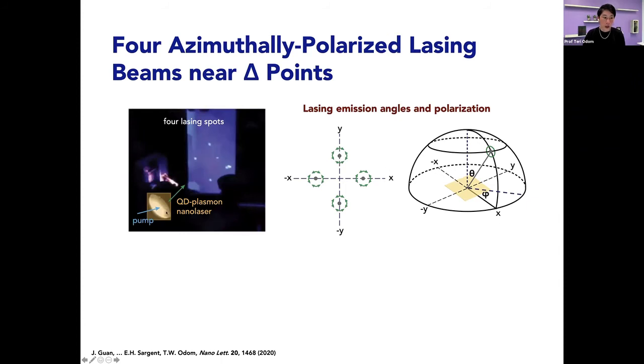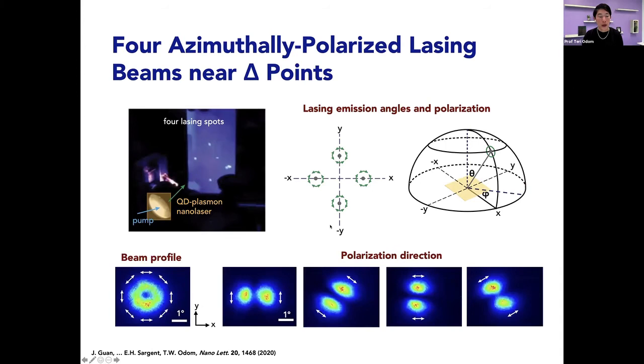And so this is what the pump looks like. These are the four lasing spots, and this is the cartoon of what the emission properties look like. We're able to achieve four azimuthally polarized lasing beams near the delta points. These are all about 19 degrees from the center. So this is pretty neat, and we can also test the beam profile characteristics again.